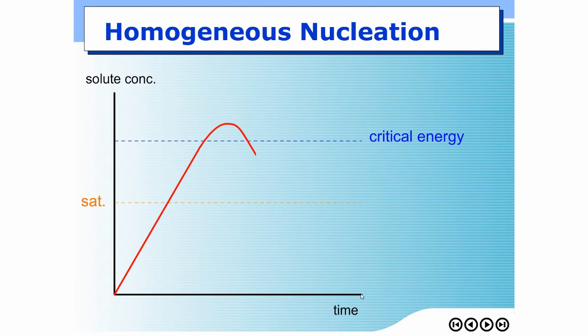Of course, at one spot in your beaker or in your system, nucleation might form, while another location might not yet form nucleation. So the concentration of growth species can still go over that point. But from this point on, nucleation already takes place. Once nucleation takes place, the concentration of growth species will start dropping. I mean the concentration in the liquid phase. Okay? It starts dropping because the extra growth species form into solid, and solid is not counted in the concentration of the solution.